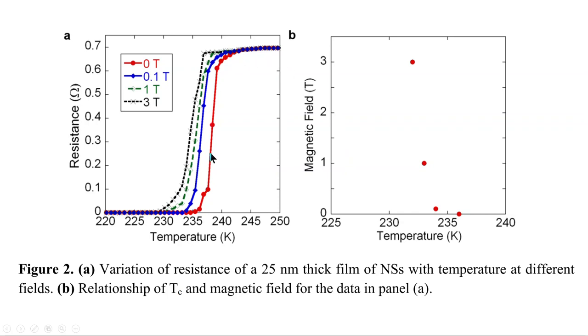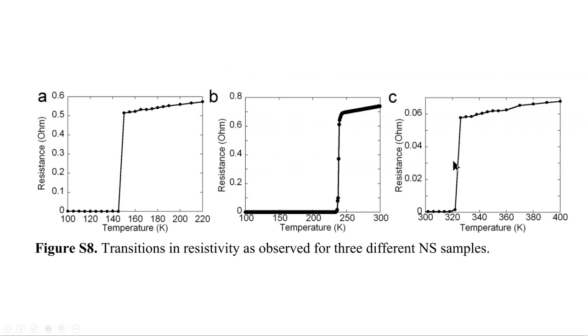And the most striking signature that they claimed is related to superconductivity is a resistance of these films as a function of temperature, showing a very sharp drop, which appears to go to zero below a critical temperature. And this temperature depends on the sample, and in particular, they report one device that has a transition above room temperature. So this is a very striking result, and if it were reproduced and really true, it would completely transform all of electronics, and it would have an enormous impact globally.